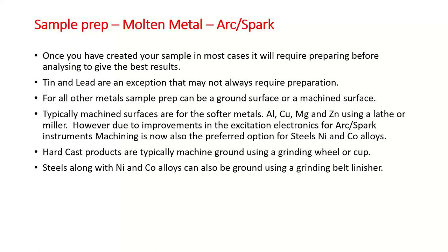You grind the sample with a grinding wheel or a grinding cup, typically because these are so hard that if you use a belt grinder, you're going to wear the belt out in one or two samples. So it means you're going to be changing your belt all the time. Steel samples, nickel and cobalt alloys, they can be prepared using a grinder or a belt linisher. But now that instrumentation has moved on and the electronics for the spark has got better, we're finding that, again, the machining of the sample with either a lathe or a milling machine is better for giving you results that are much better, especially for the gases, for low carbon, phosphorus, sulfur. So rather than using the linisher or the grinding belt.